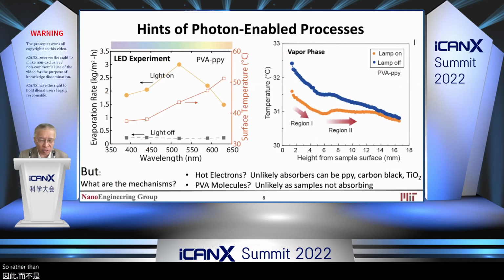So rather than using solar, we started to use light emitting diodes, LEDs, because they have a different wavelength. And to our surprise, on the left, you can see that the evaporation rate actually depends on wavelength. It peaks at the 520 nanometer LED wavelength, that's green light, where water absorbs the least. So that's a hint this might be some photon effect. But we didn't know what the photon effect was.